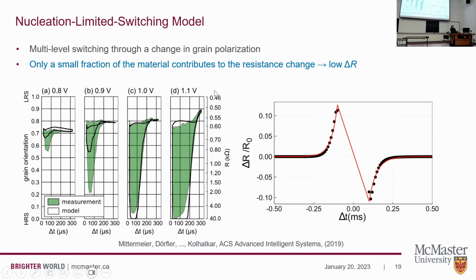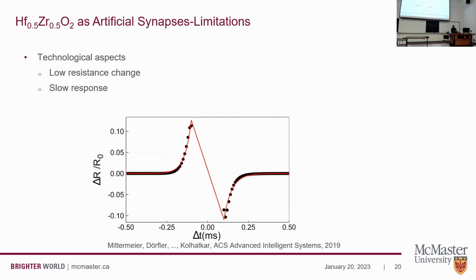If we look at the plot that I show here, the voltage on top corresponds to the amplitude of the action potential, and the color corresponds to the switching. So, we could reproduce the learning process of an actual synapse. But the resistance change that we see is still very low. And the response here, this white area, indicates a slow response of our synapse.